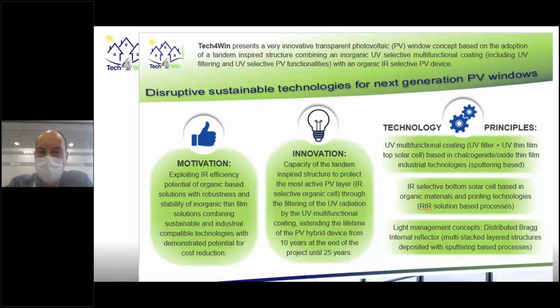The main innovation of the project relies on the capacity of this tandem-inspired structure to protect the most active PV layer, which is the infrared selective organic cell, through the filtering of ultraviolet radiation by the ultraviolet multifunctional coating. What we want in this way is to extend the lifetime of the hybrid PV device from 10 years, the target defined at the end of the project, to 25 years, which could be the long-term target. We are using processes compatible with industrial deployment. Essentially, we are using two kinds of processes: sputtering-based processes for the deposition of the ultraviolet multifunctional coatings and of the multi-stacked layer structures integrated in the distributed Bragg reflector, and printing-based technologies or roll-to-roll solution-based processes for the development and manufacturing of the infrared selective bottom solar cells.